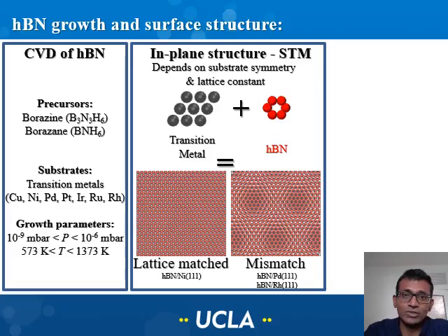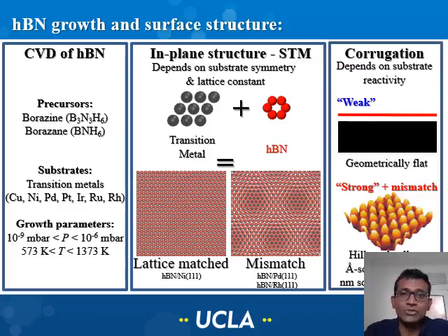And in case of hexagonal boron nitride, which is lattice matched with nickel-111, one can obtain areas without any corrugations, or on substrates where there is a large mismatch. For example, on palladium or on rhodium-111, one obtains moire patterns. And it has been shown that the corrugations associated with these moire patterns depend on the substrate composition, and one can realize either weak interactions between the substrate and the layer, leading to an atomically flat layer, or a highly corrugated surface if there are strong interactions and a large mismatch with the substrate.